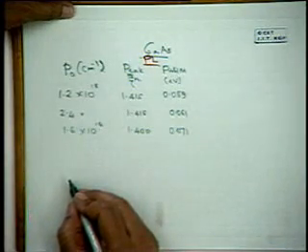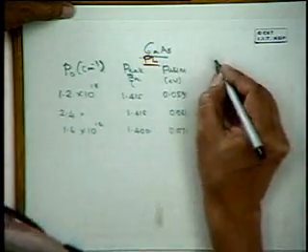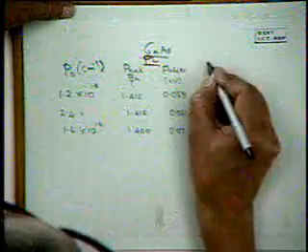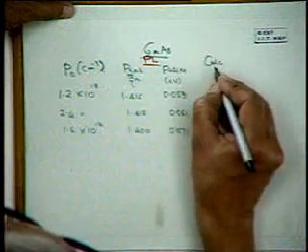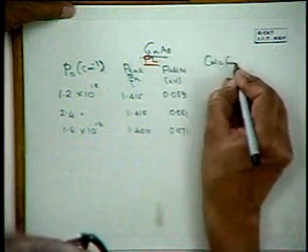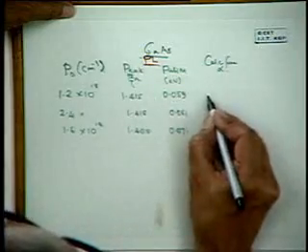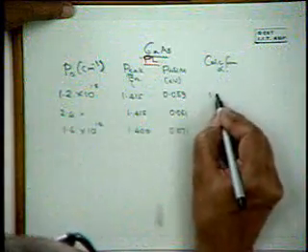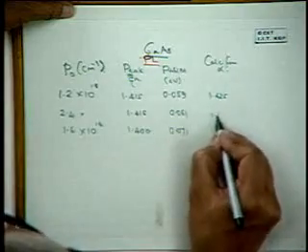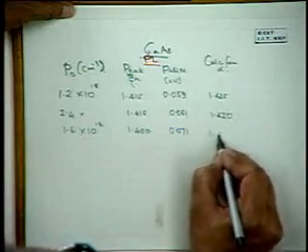Now suppose we do calculations from alpha. The peak position then will be 1.425, 1.420, 1.405. Okay, so exact values do not match, but there is the same trend.